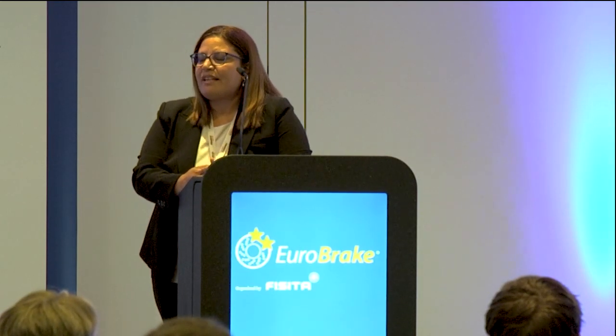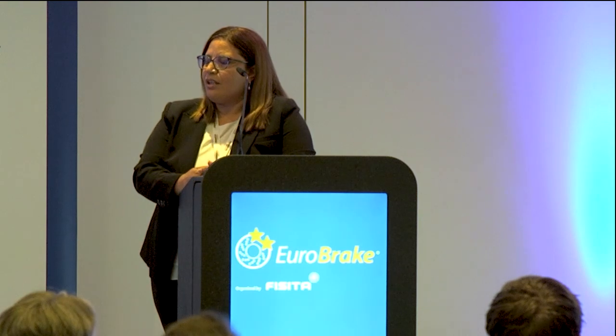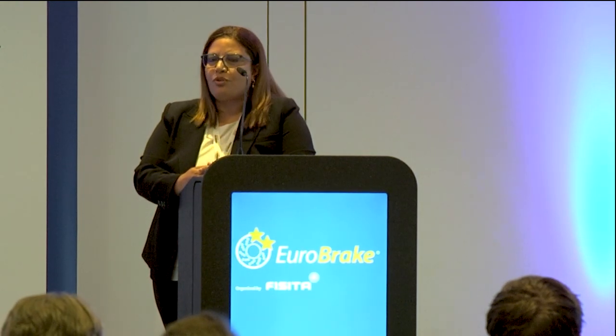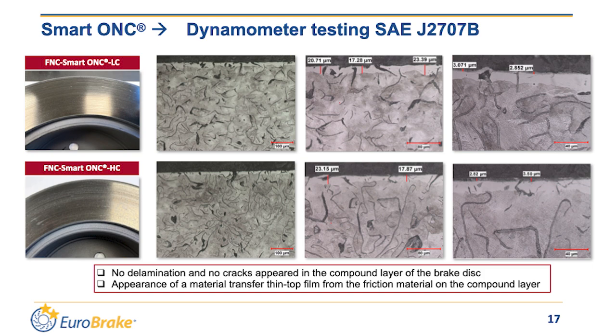The micrographs of cut samples on the friction surfaces reveal that the compound layer was not worn off after dyno test. Contrary to expectation, the thickness of the compound layer is still the same before and after testing. And we can see that there are no cracks, no delamination, and no pores that appear on the compound layer. In addition, there is appearance of a thin top layer that formed on the compound layer, which is due to material transfer film from the pad to the friction surfaces of the discs.